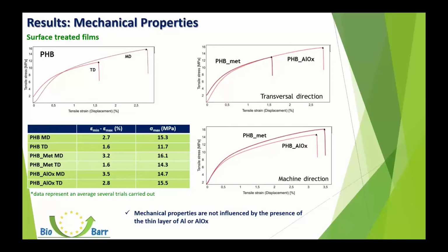Now I will present the results of the characterization. In particular, I will start from the surface-treated film, comparing to the pristine PHB that is used as a reference to compare the data. As you can see, the value both of elongation at break and tensile strength of the PHB are very low, and also the same trend we have for the surface-treated films, as the thin barrier layer is not able to increase mechanical performances of the PHB.